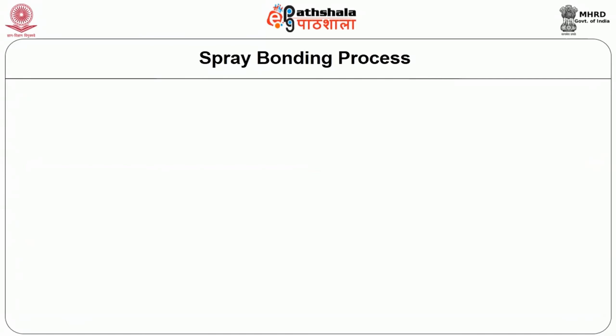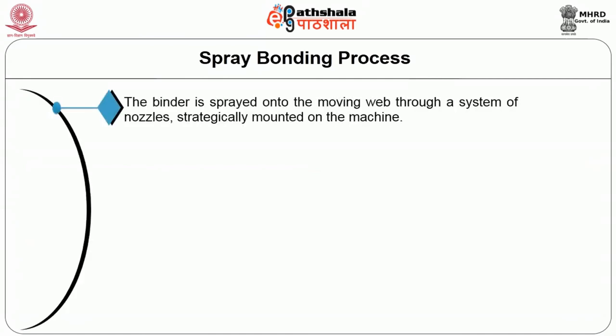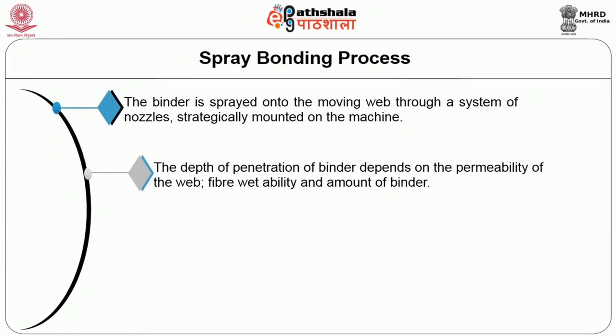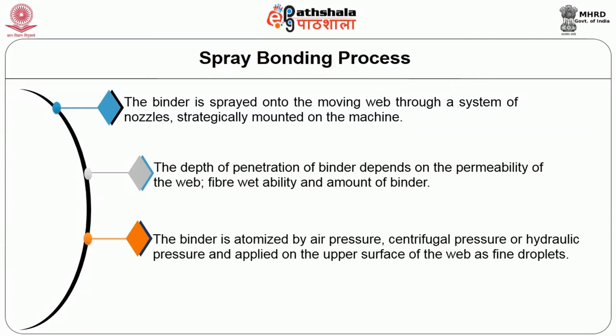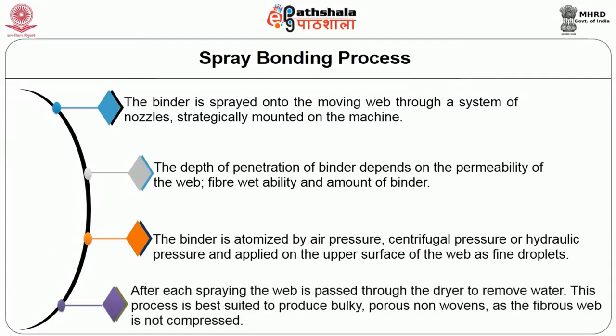The spray bonding process. In this process, the binder is sprayed onto the moving web through a system of nozzles strategically mounted on the machine. The depth of penetration of binder depends on the permeability of the web, fiber wettability, and amount of binder. The binder is atomized by air pressure, centrifugal pressure, or hydraulic pressure, and applied on the upper surface of the web as fine droplets. After each spraying, the web is passed through the dryer to remove excess water. This process is best suited to produce bulky, porous nonwovens, as the fibrous web is not compressed.